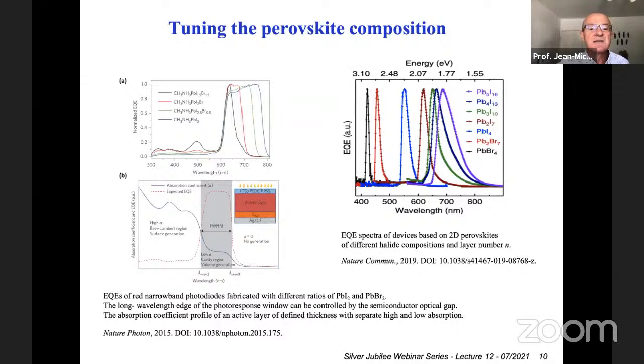And then, in that paper, they were also using different active layer thicknesses. The composition is tuning the band gap more or less into the infrared, into the red region, and they use the thickness of the material, which allows reducing the range of absorption, to cut down the part of the absorption that is in the blue region.